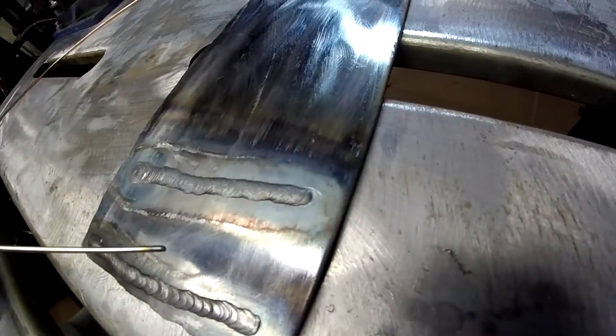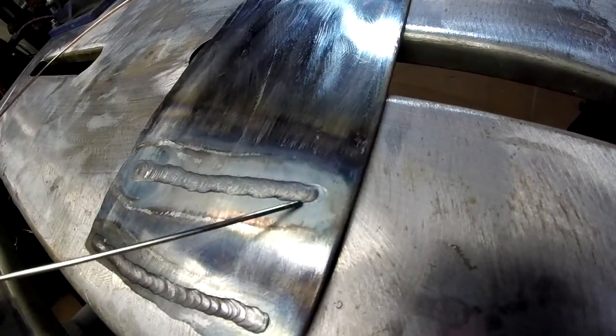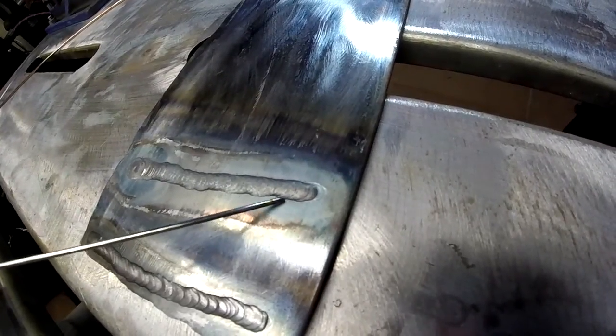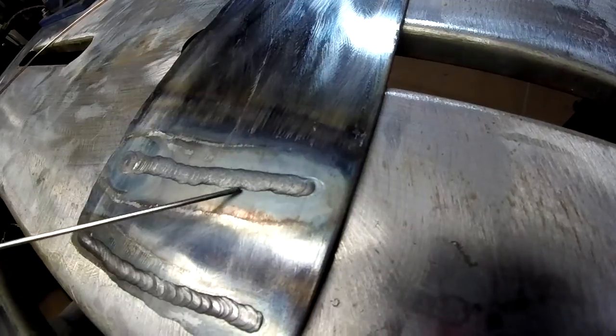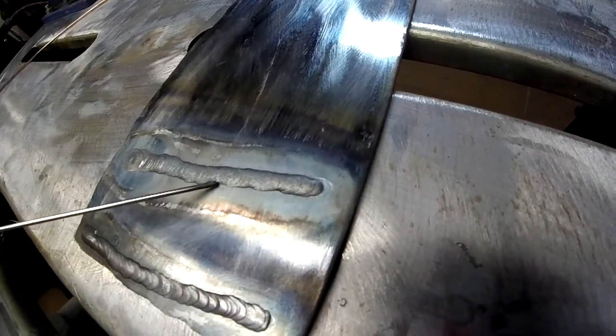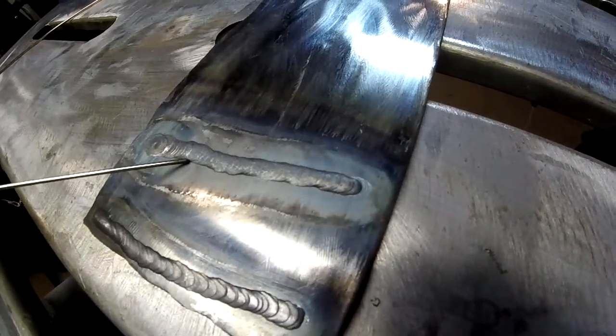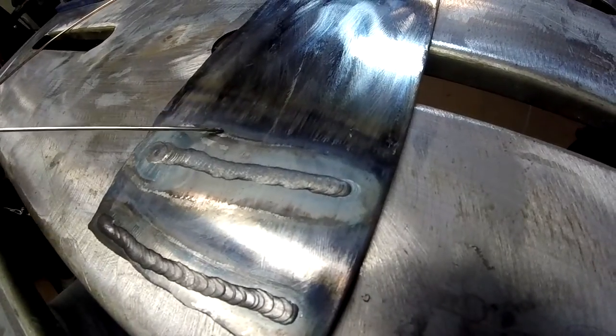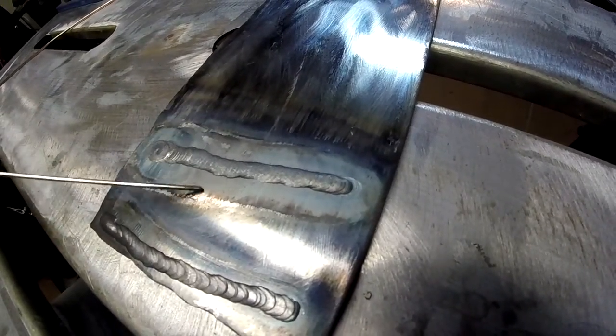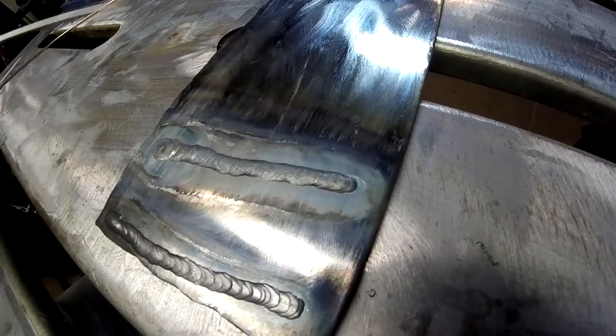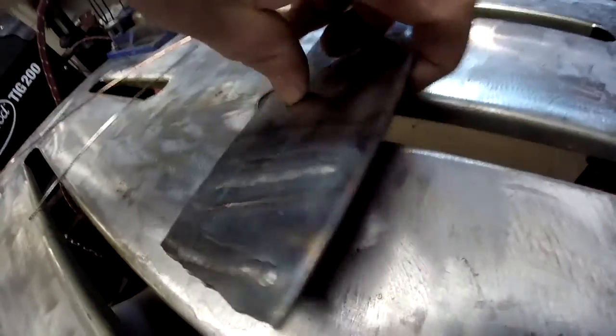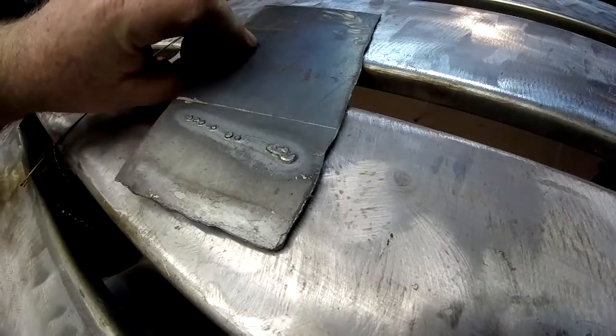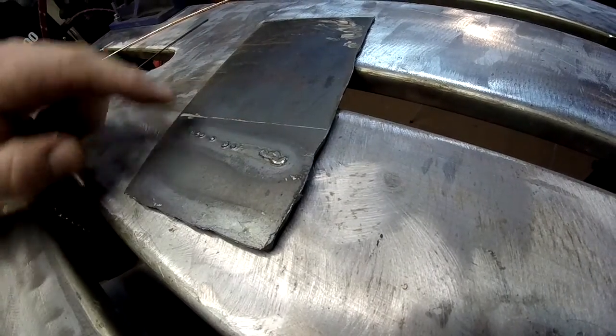Now, let's look at the long arc length. You can hardly see any differentiation in the ripples. The weld looks dull and gray. Here to the end, we're almost completely melted in. And that heat affected zone is well over an inch. And if we flip it over, you can see we began to melt through.